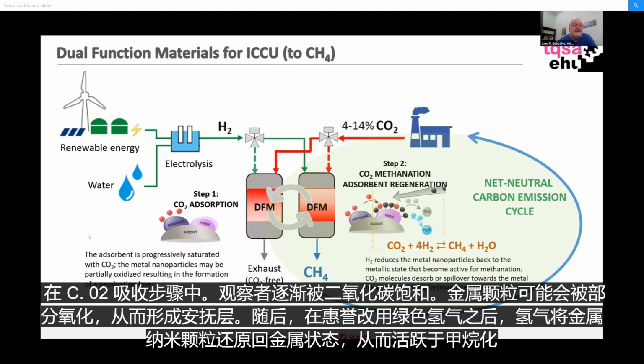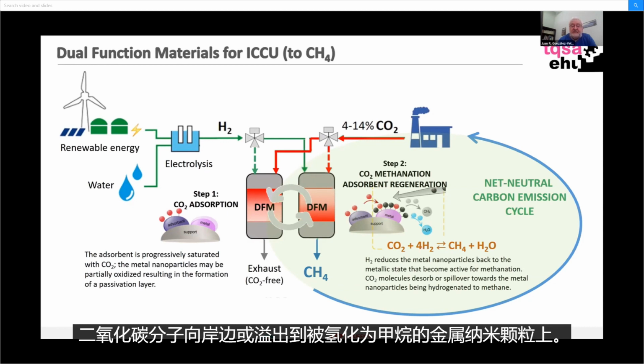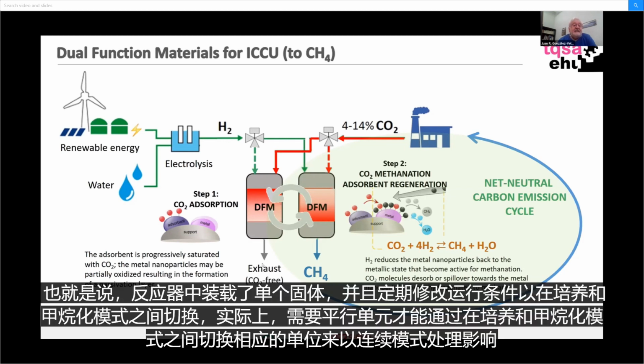During the CO2 adsorption step, the adsorbent is progressively saturated with CO2. The metal particles may be partially oxidized, resulting in the formation of a passivation layer. Subsequently, after feed switching to green hydrogen, the hydrogen reduces the metal nanoparticles back to the metallic state, which become active for methanation. CO2 molecules desorb or spill over towards the metal nanoparticles, being hydrogenated to methane. Thus, a single solid is loaded in a reactor, and the operating conditions are modified at regular intervals to switch between capture and methanation modes.